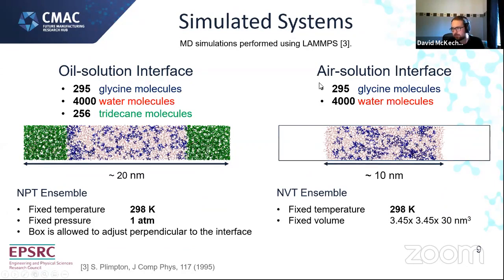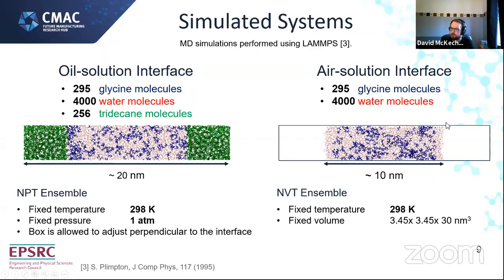We used molecular dynamics simulations run using LAMMPS to simulate both the oil-solution interface and the air-solution interface. Glycine molecules are shown in blue, water in red, and tridecane in green. For the air-solution interface we ran NVT with a vacuum layer on either side to represent air. In both cases the concentration is approximately 307 grams per kilogram, run at 298 Kelvin and one atmosphere for the NPT oil-solution interface.